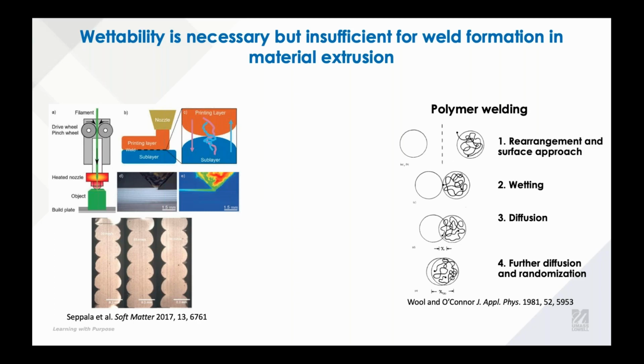And so the first condition for this welding to occur is that we have to have rearrangement and surface approach. If we don't have intimate contact between the two sides, then we don't get any welding. And then the next step here, assuming that we do have this intimate contact, is that we'll have wetting. And so here the condition would be that you would have surface energies that facilitate wetting of your molten polymer onto the cooled polymer below it. And then over longer time scales, assuming that the wetting condition is met, then we have diffusion, and then over time, assuming that you use full reptation, then we have randomization of these polymer chains. So this is typically the way that we think about what's happening in material extrusion. Next slide.